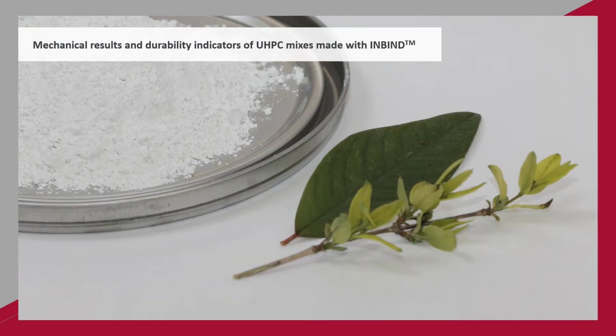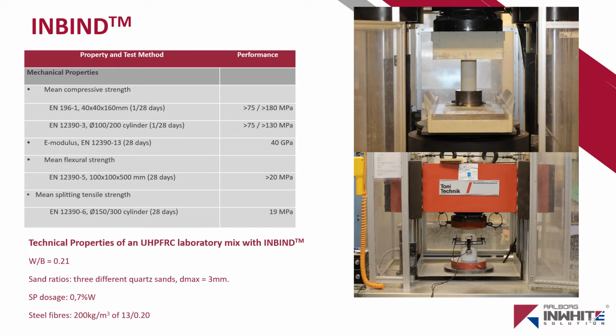In the next slides, I will show some mechanical and durability properties that UHPC mixes with InBind achieved. In terms of mechanical properties, we were able to achieve mean compressive strength of more than 130 megapascal in 10 by 20 centimeter cylinders, with flexural strength of more than 20 megapascal. This mix has a water to binder ratio of 0.21, three sand ratios, and 200 kilos per cubic meter of steel fibers. By changing the sands and water to binder, different mechanical values will be achieved.